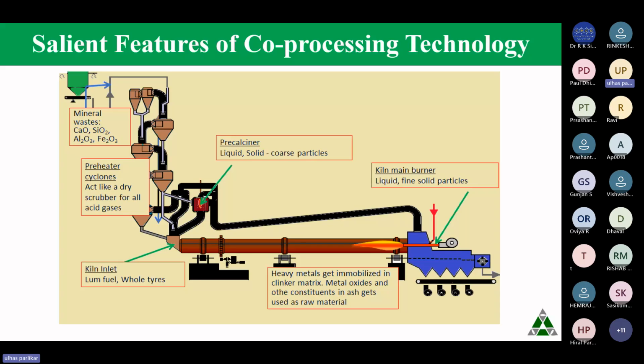Nothing will go out. The combustion efficiency of this cement kiln is very high, in the sense that the incinerator requirement is 4 nines, that means 99.99% destruction of the organic material as per design. We have measured the combustion efficiencies of the cement kilns, and they are up to 9 nines. That's the kind of capability the cement kiln has got, and therefore there's absolutely no cause of concern on emissions like dioxins or furans or any other kind of acidic gases or VOCs.